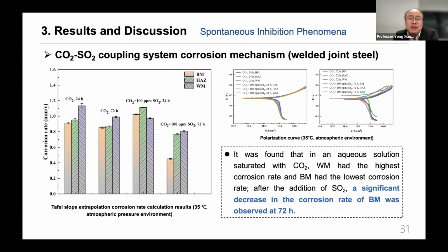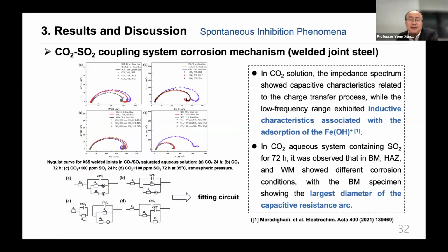So we also did the same work for the welded joint steels, and we also found the same things. That is the base metal: when SO2 goes into the system, the base metal also reduced its corrosion rate after about 72 hours of exposure. So we repeated this experiment. We found the same law, that the base metal has a very low corrosion rate compared with other parts like the HAZ and WM.